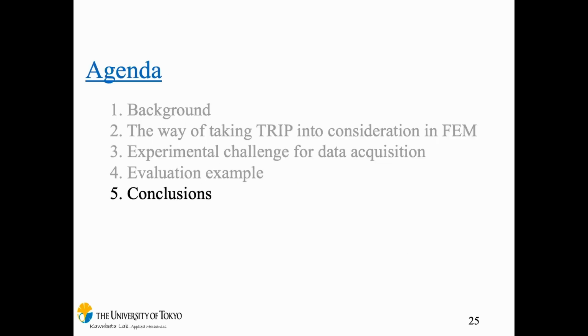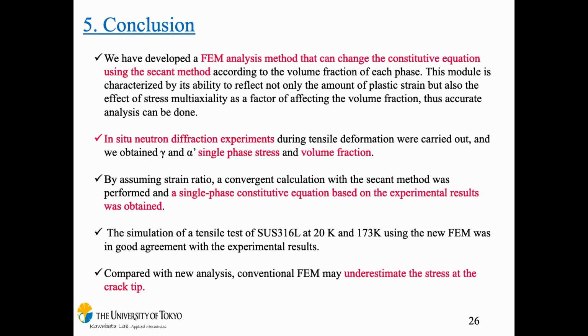Okay, this is the conclusion. We developed a new FEM method to consider the TRIP, and in-situ neutron diffraction experiments were conducted to get the single phase stress and volume fraction. And assuming the strain ratio, we can get the single phase constitutive equation. And finally, we conduct some FEM analysis and get good results. And in the conventional FEM, the stress may be underestimated at the crack tip.